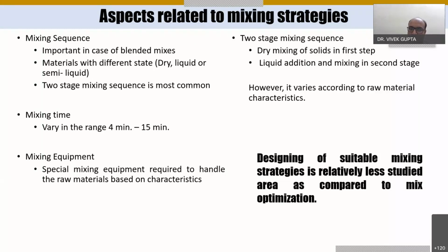The mixing time varies in the literature from 4 minutes to 15 minutes, and in some cases special mixing equipment is required to handle the raw materials based on their characteristics. One great example is from SVNIT Surat, where Professor Raut proposed a specific mixer for handling paper mill residue. That is very interesting, and if you want to go into detail, you can look at it. They proposed a particular mixer for handling the waste. We also worked on blending equipment. I will show that in the upcoming slide.